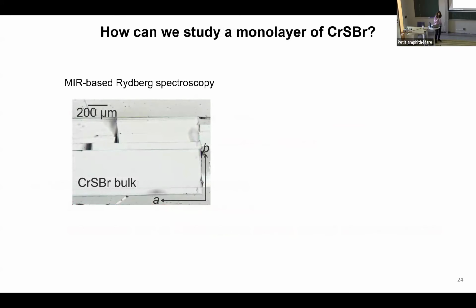So the sample that I was talking about so far, the bulk chromium sulfide bromide, was this large. It is a few hundred microns in width and length, and it is large enough to be easily used in whatever spectroscopic technique, because the diffraction limit of even mid-infrared or terahertz radiation is smaller than the size of our sample. So we can really study our sample in a background-free manner.